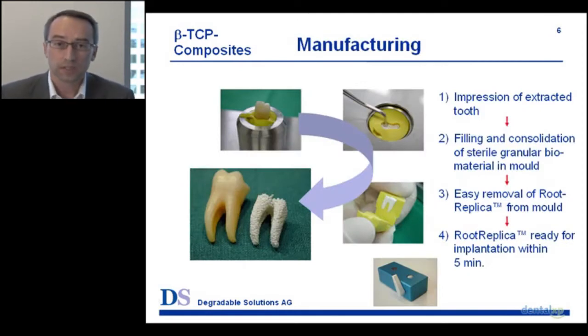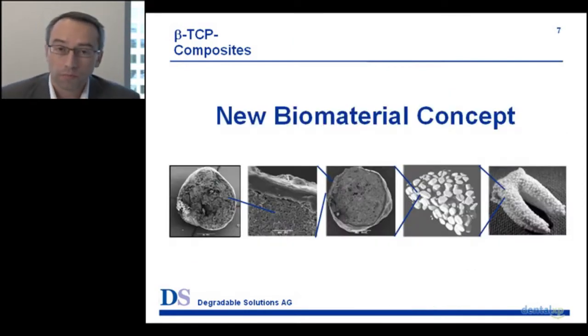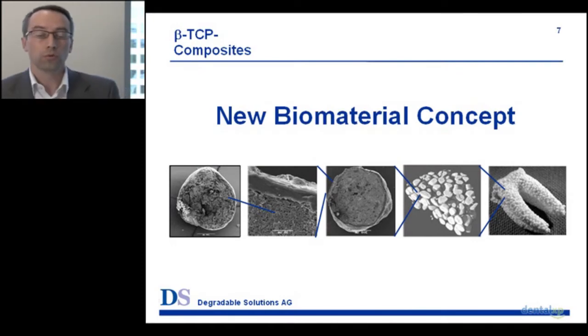The idea, as you can see in this slide, was to make an exact copy of the tooth root in a silicone mass, to fill this negative with a biomaterial that would harden, and then you have this exact copy, as you can see in the picture on the bottom left. This is plugged back into the extraction site just about 5 to 10 minutes after the extraction was performed. So to do that we had to develop a new biomaterial, and I would like to go through this development with you in the next slides.